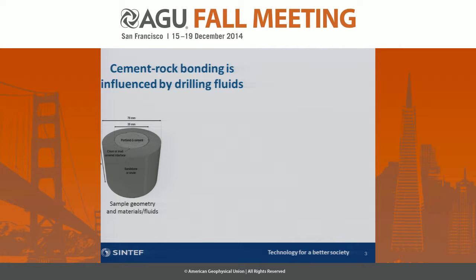So what we did in the big CCS project was that we wanted to try to find out what the size of the apertures of these leakages are. So how large are these microannuli that people are talking about, and why and where do they most likely occur in a well? So what we did was to first make some small samples, as you see here, with a hollow rock cylinder with cement inside. And then we varied the surface properties of the rock, so they were either mud-covered or clean. And we used two muds that are very typically employed, oil-based mud or water-based mud, both commercial muds that are used by industry. And then we scanned these samples using microcomputed tomography, and then reconstructed them in 3D.